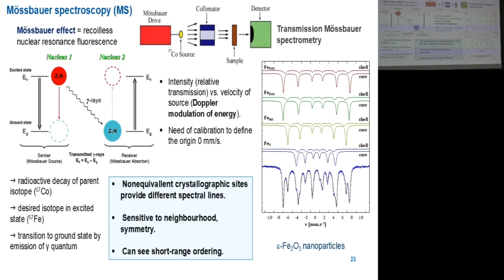And the resulting spectrum contains quite rich information, because in the first approximation, let us conclude that all crystallographically non-equivalent sites of iron will be manifested by a separate component in the spectrum, by a separate subspectrum. So, for example, in this case, epsilon iron oxide, this structure has four iron sublattices, four crystallographically different sites. So we have four components in the spectrum related to these different iron positions.